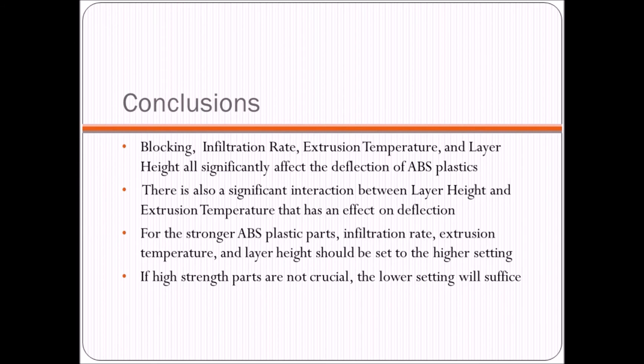So whenever you're deciding what settings you're going to set your printer on, this is something you should consider. For stronger ABS plastic parts, all of the factors should be set at their higher setting. It's important to note that at the higher setting, especially for infill rate, it significantly increases the time that the part is going to take to be printed. And that makes sense because you're physically laying more plastic down. So that just takes more time. So it's important to note that if the strength is not crucial for the part, then it might be a good idea to set the infill rate on the lower setting.